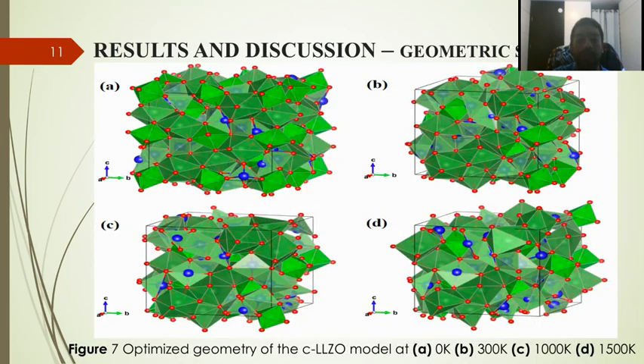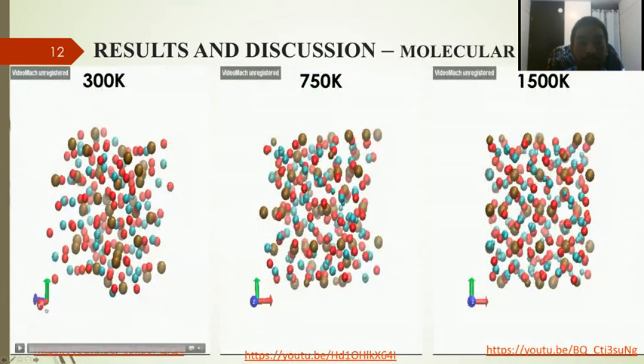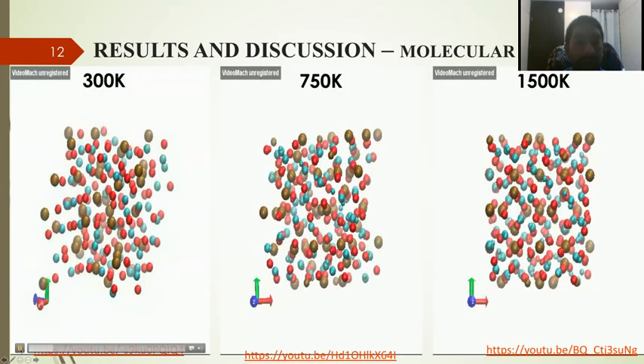So as we increase the temperature, our ordered geometry becomes disordered. And this is the clear indication from this figure. So number A is for zero Kelvin, and number D is for 1500 Kelvin. Next, please. So this is the molecular dynamics.